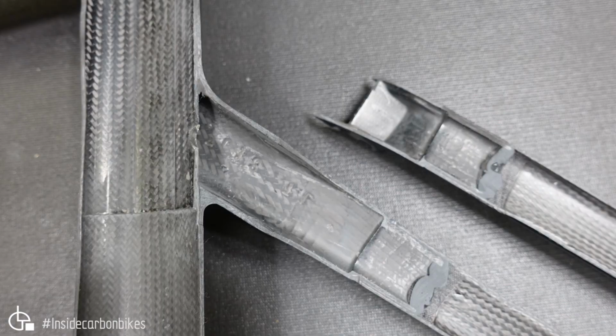Okay, so here we have the seat stay junction to the seat tube. You can see the bonded joint through here. Adhesive spew out there. Again, really nice control of the bond line thickness. No voids in the adhesive. All that looks really clean. You've got nice steps in terms of the ply drop-offs. You've also got a rib through here, which is the same as what we had on the chainstay, and that's where the brake bolt goes through, and that acts as a bulkhead to stiffen that area and provide really good compressive load strength through that. So that's a really nice feature.